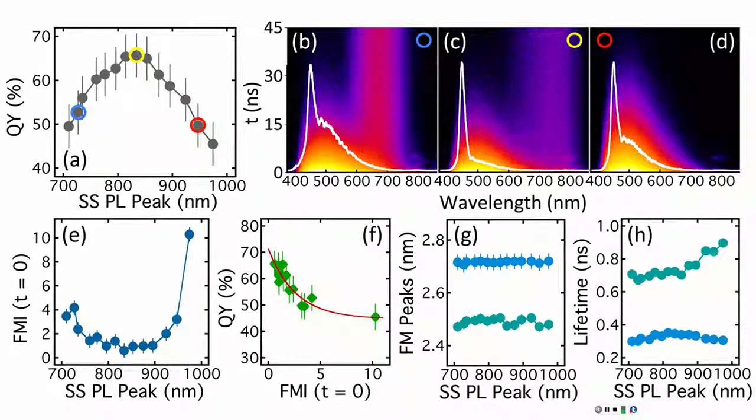That's exactly the point. That's the opposite though. Their band gap is not affected by the confinement. This is what they see in the experiment. Well, if you get the band gap low enough below those trap states... But this peak appears at around how many? 450 probably nanometers, and it's not really shifting anywhere. If you increase the size, then your gap becomes very much redshifted, right, and then it will be very far away. You cannot really see them in the same range anymore.